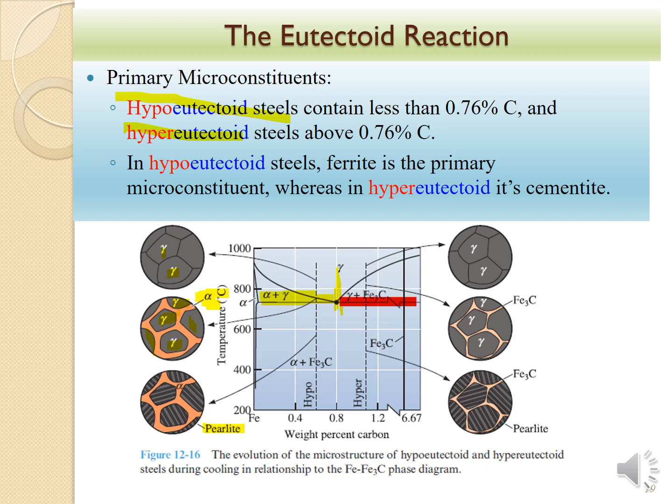On the other side, we have hypereutectoid. Again, initially we just have all solid austenite, and passing through the solvus line, we will have the two-phase region where the cementite will precipitate out from the solid austenite phase.